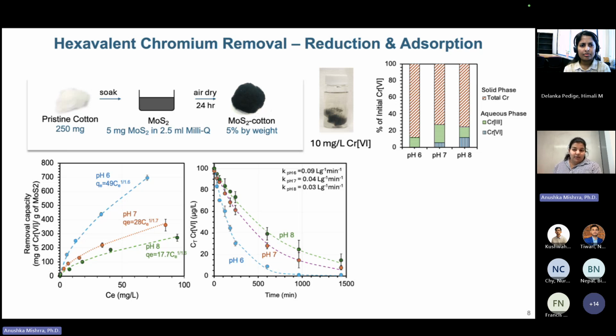And when we were able to load more chromium into the water, we could start seeing the different oxidation states. So the red bar over here on the right, the bar chart - the red region shows all the chromium that is on the material, and the green part of it is chromium 3 that is in the water after the reaction has taken place, and some of the remaining chromium 6 in the water after the reaction has taken place can be seen.